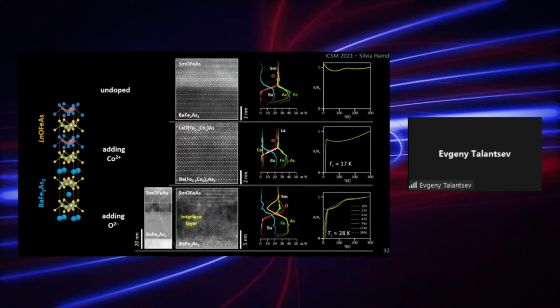One type of heterostructure is a clean interface, and this clean interface is not altered by adding cobalt. And when we add cobalt, cobalt is known for electron doping. It can electron dope the iron oxynictide, and it can electron dope the barium 122. And in both cases, we have a doped layer, the upper layer and the bottom layer, and the superconductivity has signatures of a 3D superconductor. So we can assume that both layers are superconducting and share just the average TC.